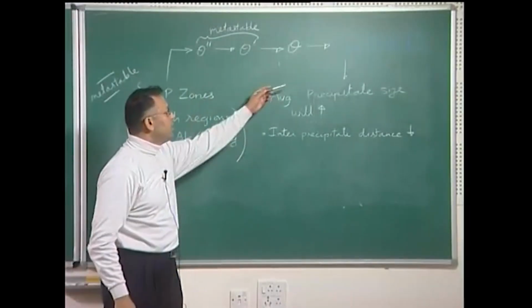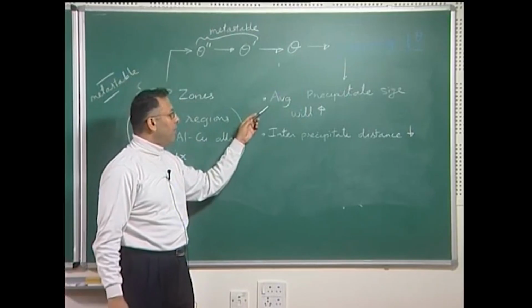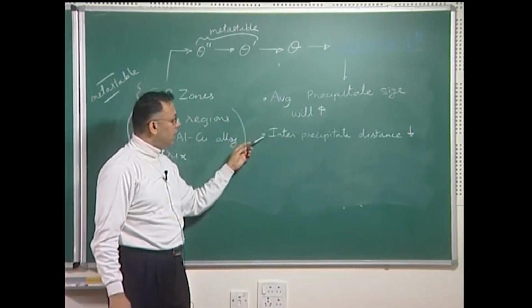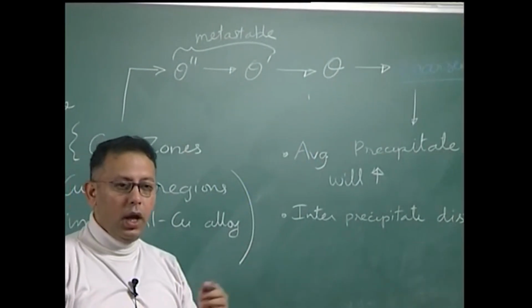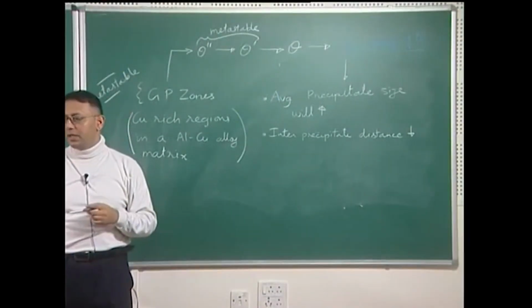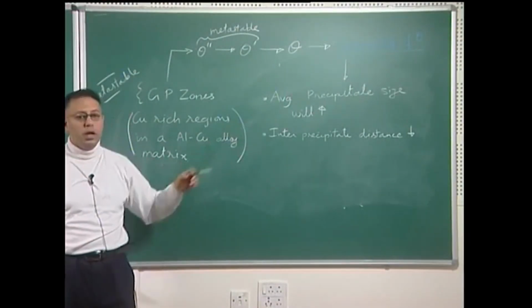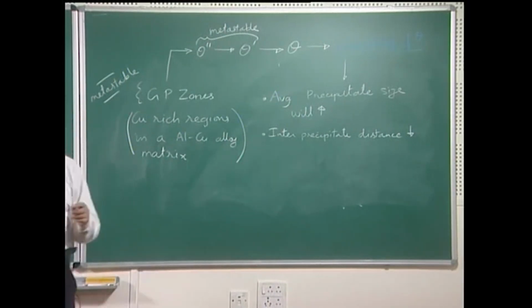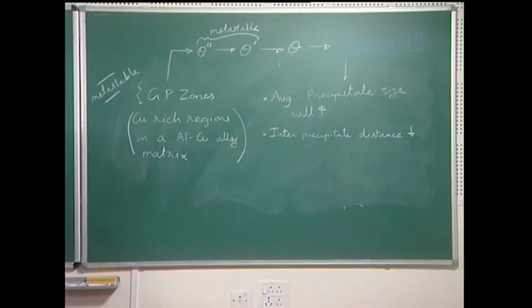So, during the coarsening process, two things would happen. The average precipitate size will increase and the interprecipitate distance would increase, and in a numerical example later on we will see that this is actually going to be deleterious for the hardness or the strength of the material.